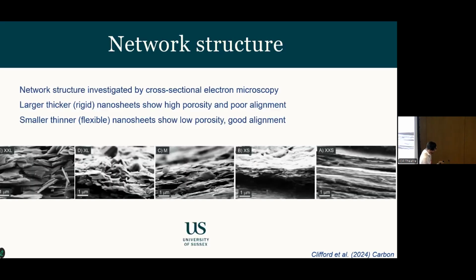So we started to think about why that might be the case. When we look at the different size fractions in SEM, for example, we find that the big sheets sustain larger pores because they're large sheets, they're rigid, while the smaller sheets are flexible enough that they actually conform to each other. And so they reduce the porosity. But in reducing the porosity, we also likely lower the junction resistance between the sheets.